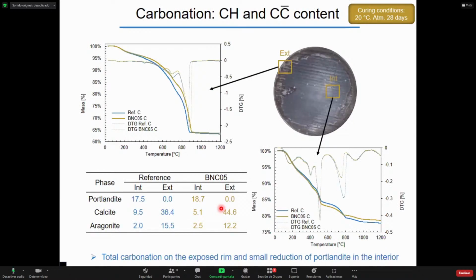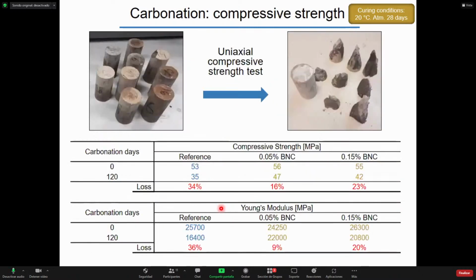The reduction in porosity and the precipitation of a stronger material in pores may lead us to believe that strength will increase over time. However, this is not the case for our samples. After 120 days of carbonation, we saw that compressive strength was reduced by 34% on the reference samples, and for the bacterial nanocellulose samples, it reduced 16% and 23%. We saw a similar trend on the Young modulus, where the reference sample lost 36%, and the other mixtures lost 9% and 20% respectively.